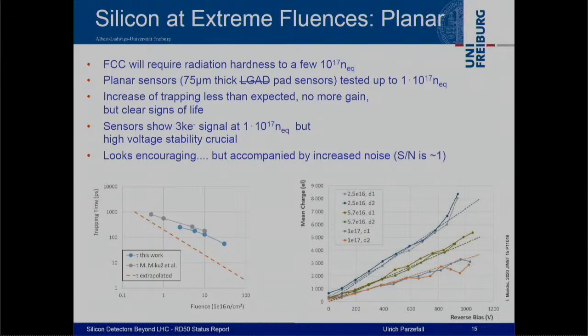So that is one part of good news. Then the other part of good news is here in this plot, where as a function of bias voltage, you look at the charge. You see that for sensors for 3 different fluences, the highest one again, 10 to the 17, there is still something like 3,000 electron signal to be collected at this high dose.